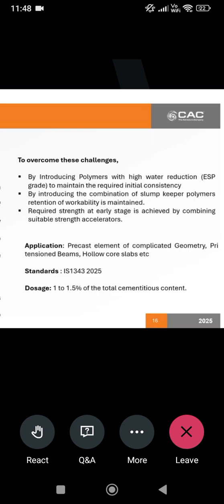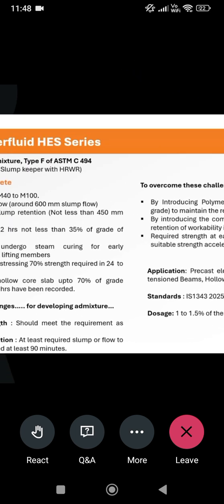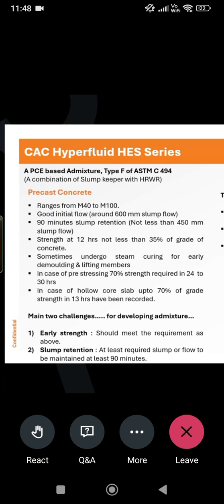And this is hyperfluid HES precast concrete. It ranges from M40 to M100. Good initial flow is required. You know that around 600 mm slump flow is required for precast, and 90 minutes slump retention is required for placing and other things, not less than 450 mm slump flow. Strength at 12 hours, not less than 35% of the grade of concrete is required. Sometimes it undergoes steam curing for early demolding and lifting members.